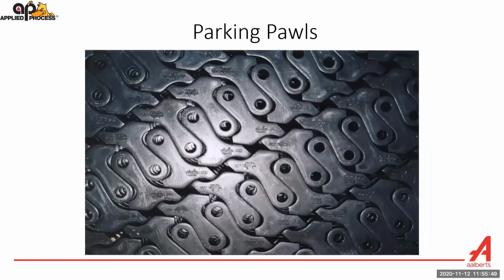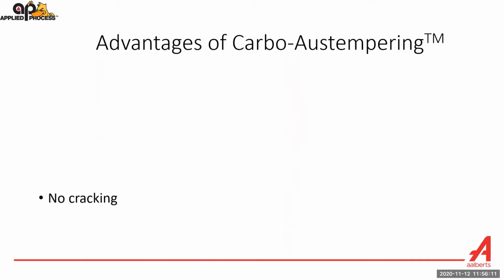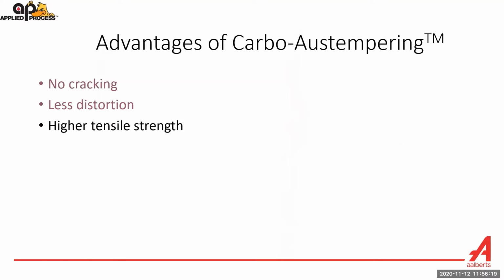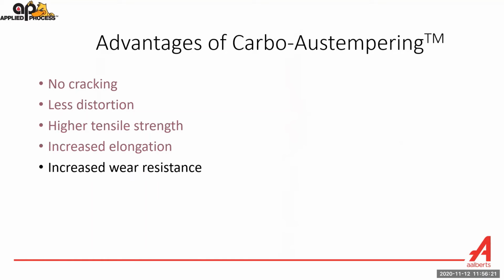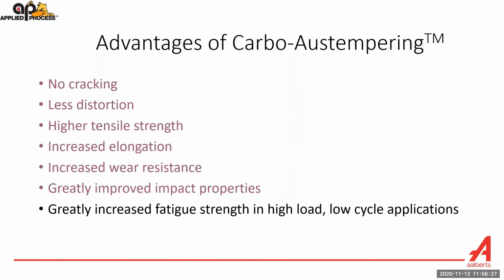And if anybody on the line has owned a General Motors pickup truck with an Allison transmission in it behind the Duramax, there's a Carbo-Austempered parking pawl in it. Scroll compressor U-arcs. So the advantages of Carbo-Austempering, again, it's very similar to the Austempering of steels without the use of carbon. It's no cracking, less distortion, higher tensile strengths, increased elongation, increased wear resistance, greatly improved impact properties, and increased fatigue strength as well.